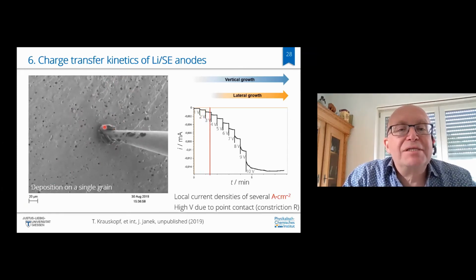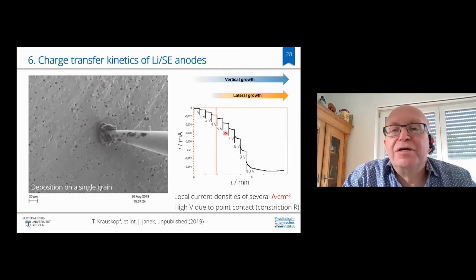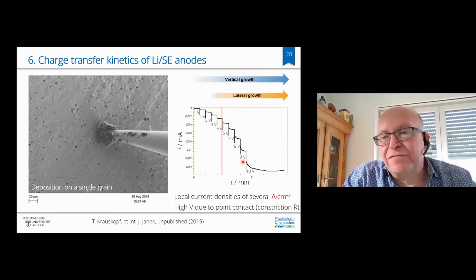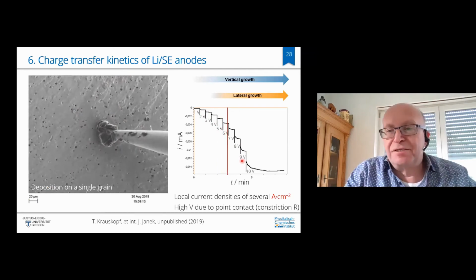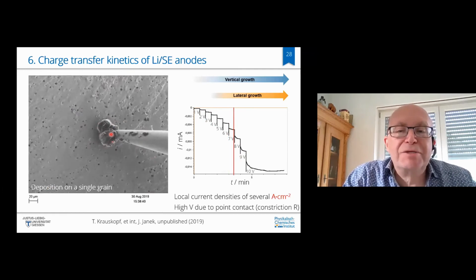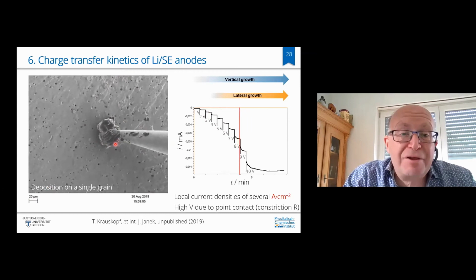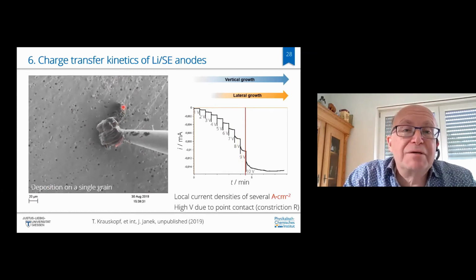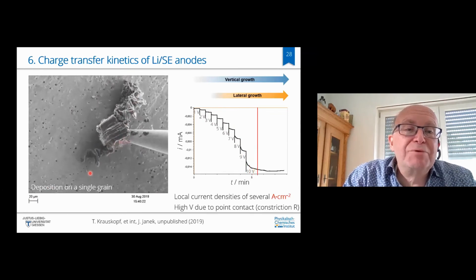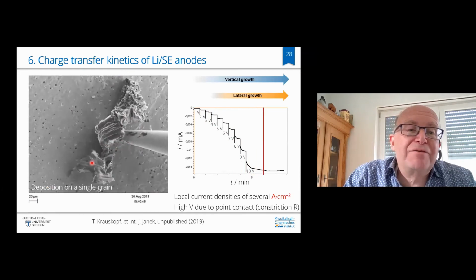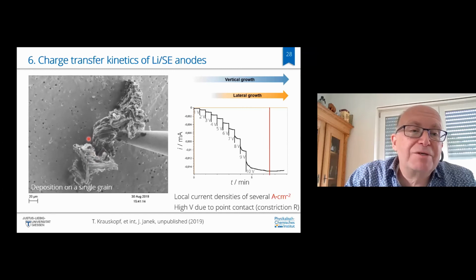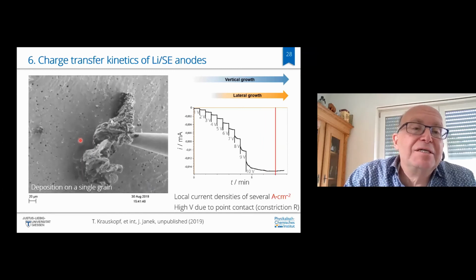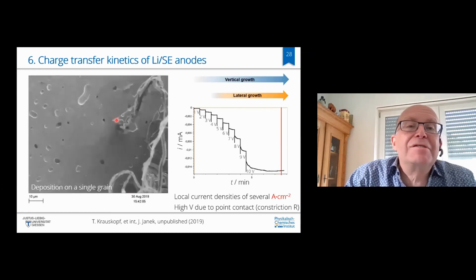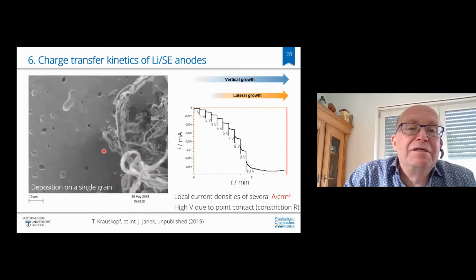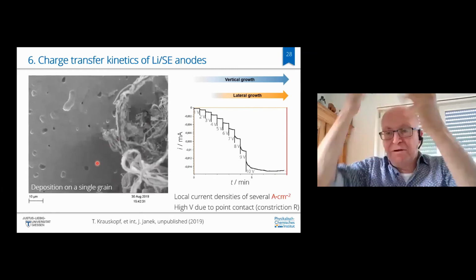What you see is we deposit lithium cathodically with increasing voltage. Don't be surprised by these high voltages. These are, of course, the voltages that are so high due to the constriction resistance of this small electrode in this electrolyte. What you see, lithium is growing and growing, and the higher the voltage gets, the faster the lithium grows. Suddenly a new growth mode comes out. So lithium shoots out quite a distance from the electrode. And if you look closer, we see the lithium is spilling out of the electrolyte in the forms of whiskers grown together. And I think what is really exciting is in a second, you see there is lithium really shooting out of the crystal, which is not directly contacted by the electrode. You see lithium wires, single crystal wires shoot out of the solid electrolyte.